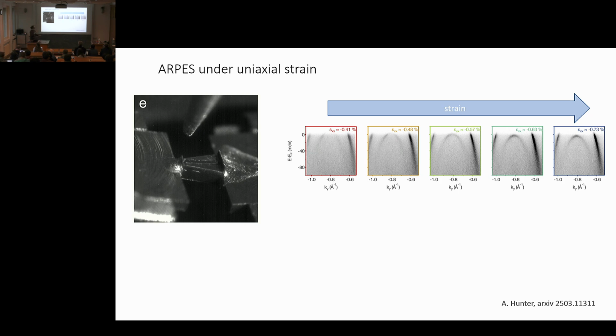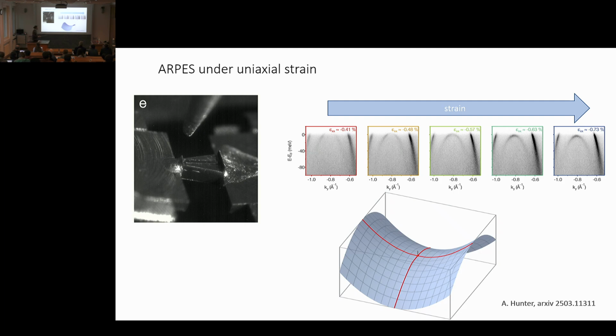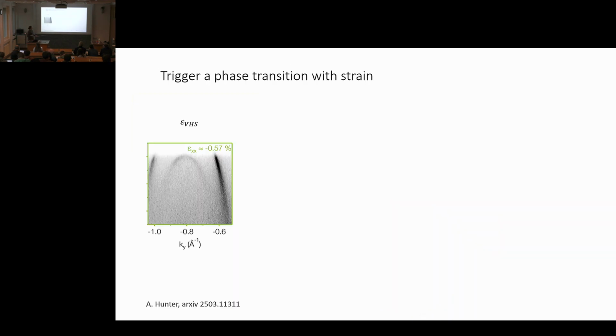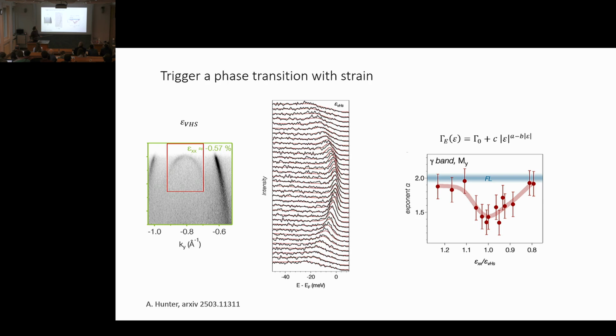In this direction, it looks like a hole-like band, but in the other direction, it's actually an electron-like band, meaning it's a saddle point which we have here. It's a Van Hove singularity to be precise, meaning we have a singularity in the density of states. Now let's check if this is actually also the same point which we have seen in transport. So we looked at the energy dispersion, this small window, at each momentum. We fitted the Lorentzian. Our Lorentzian now has a width depending on energy with the following function. And in particular, for this strain, where we saw the Van Hove singularity crossing the Fermi level, we see the dip in the exponent similar to what the transport measurements saw.